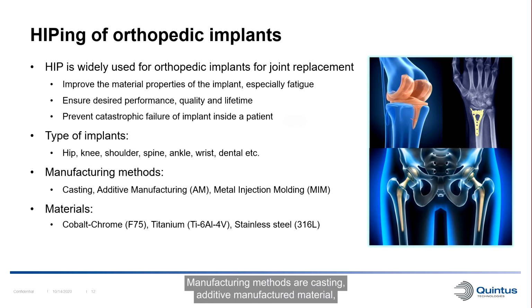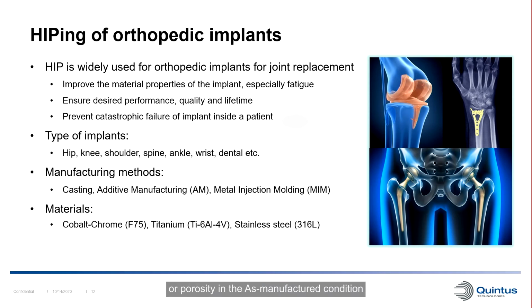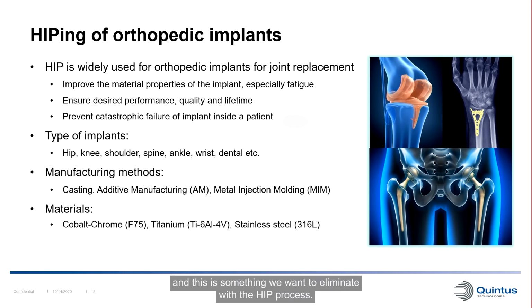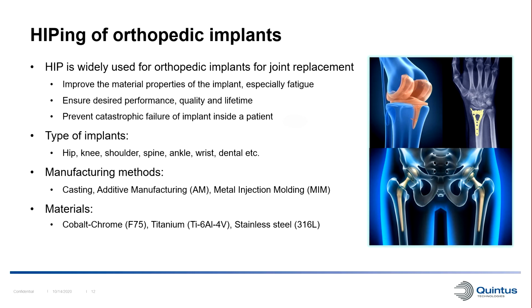Manufacturing methods are casting, additive manufactured material, metal injection molding, MIM, which is common for dental applications. And all of these processes typically have some internal defects or porosity in the as manufactured condition. And this is something we want to eliminate with the HIP process. Materials are cobalt chrome alloys, for example F75. We got titanium alloys where Ti64 is common, and then the stainless steel like 316L.